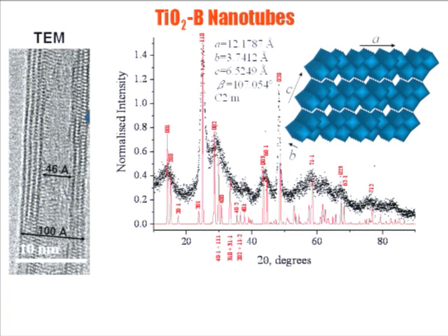If you look at these two patterns, you can see that if you broaden some of the reflections to a different extent, you will get a pattern similar to what we observed in the experiment, which was a good starting point for us. And furthermore, luckily, the narrowest reflection was a single one, 020.